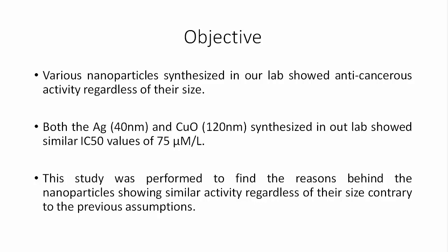In our lab, we have synthesized many nanoparticles, of which a silver nanoparticle of 40 nanometers and a copper oxide nanoparticle of 120 nanometers — were showing similar activity of 75 micromolar per liter IC50, which is the inhibition concentration showing 50% inhibition of a cancer target. Until now, nanoparticles were considered to show activity according to their size, but here we see a threefold size increase still showing similar activity.